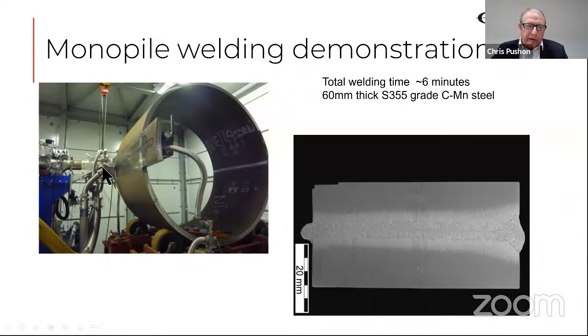So it pumps very, very quickly because of the number of pumps we have. And on the back, we have a little backing vacuum with a tiny vacuum pump that keeps a vacuum at the back of the joint. And we don't use any preheats, and there's no wire or flux or gas as a shielding. So there's no consumables apart from electricity. And here you see the weld profile. This is 60 millimeters thick, and it's in S355 grade carbon manganese steel.